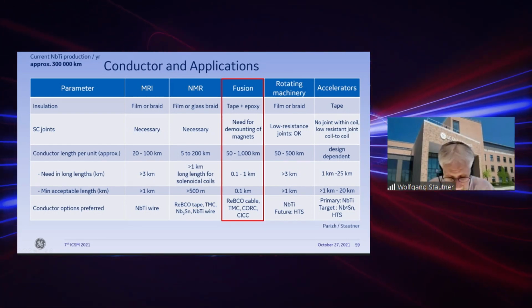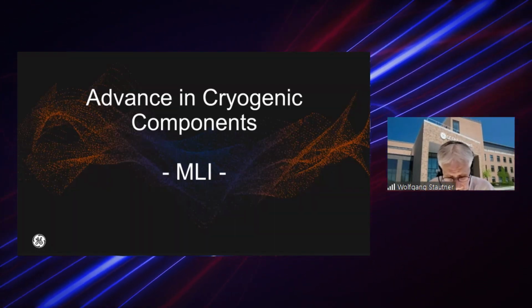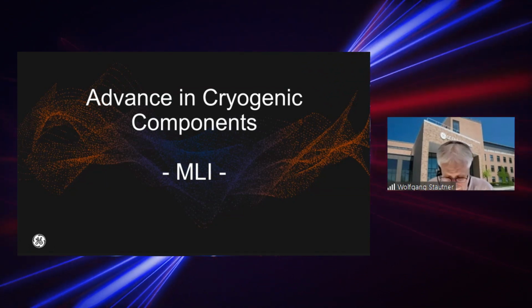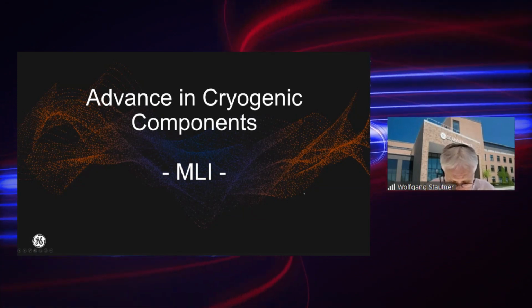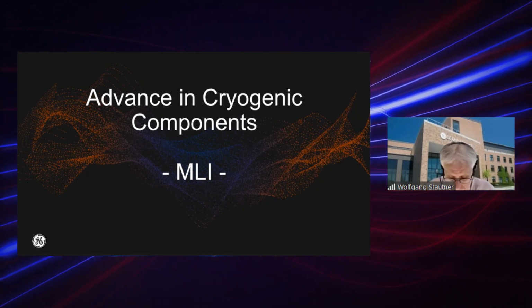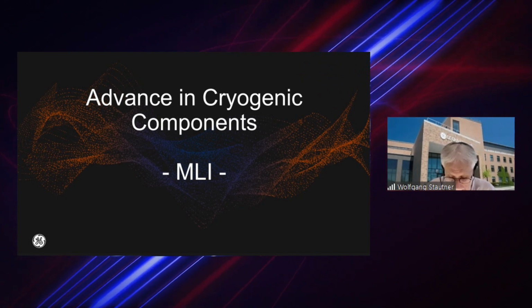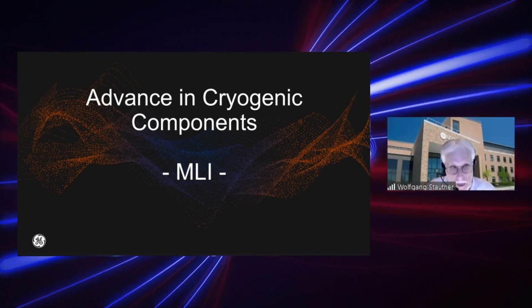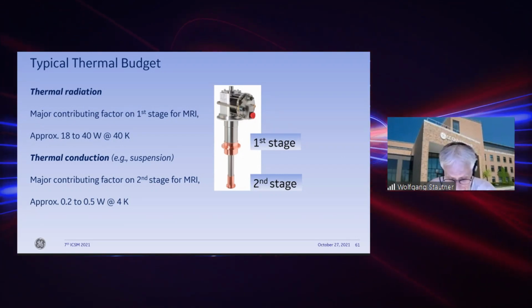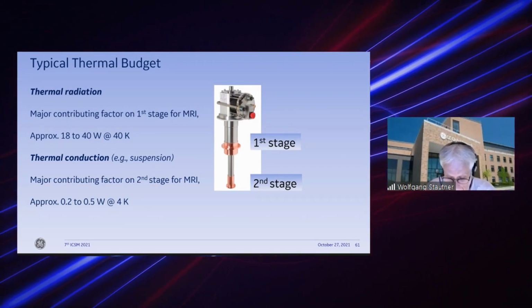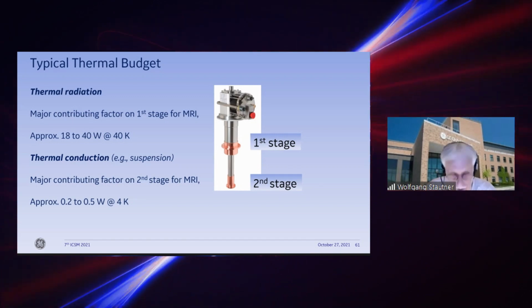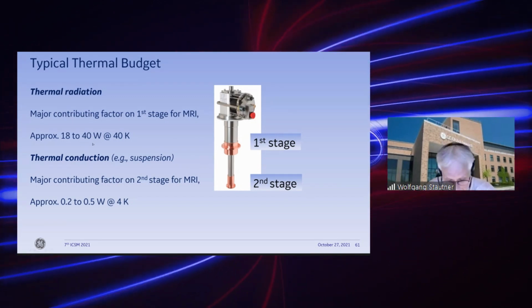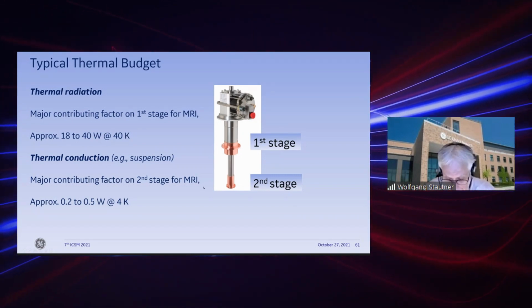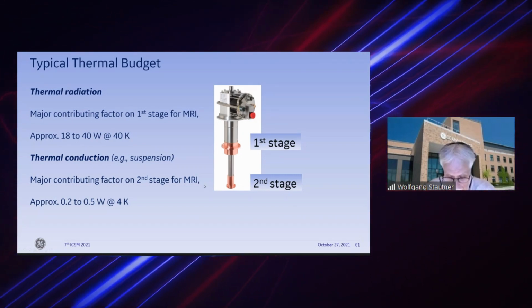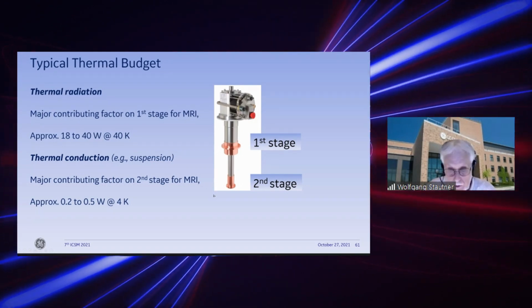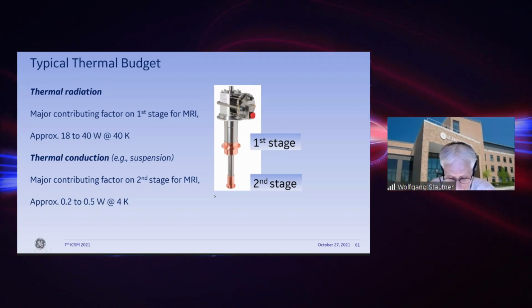Let's shift gears a bit again, and we are now diving deeper to the cryogenic component level on materials, and in particular mention a very important insulation, what we call multi-layer insulation, or in short, MLI. Let's assume that we do have specific thermal losses on a system here for an MRI system that we need to cool away. In the upper temperature region here, on a cryostat between 20 and 40 Kelvin, we have to control the thermal radiation heat losses by choosing an appropriate insulation depending on your design.